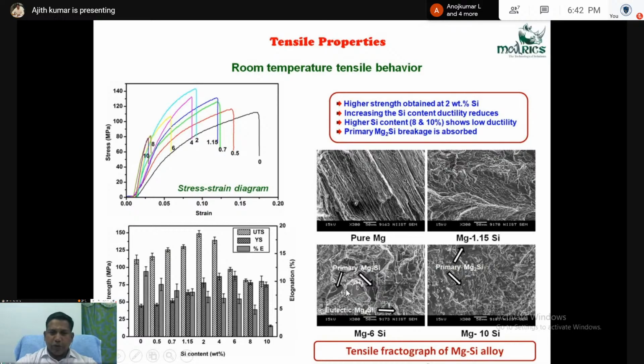The primary Mg2Si breakage we can understand using this SEM analysis, and in the case of Mg10Si, very long particle breakage we can see. So the reduction in tensile property is due to the brittle Mg2Si particles present in the microstructure. Due to that, the failure is happening.